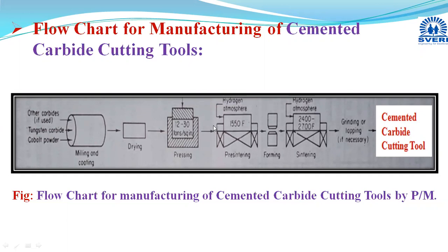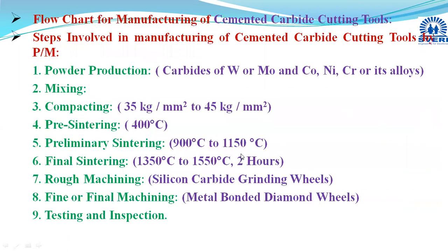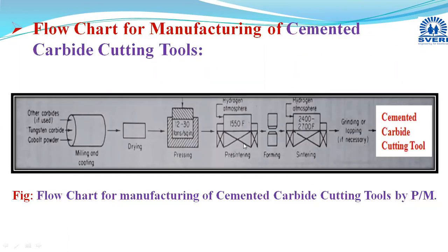Pre-sintering is done to remove the lubricants which you have added in the mixing stage for helping the pressing operation. That oil is eliminated by doing the sintering at 400 degrees Celsius, and then sintering is done in the temperature zone 900 to 1150 degrees Celsius. If required, the sizing is done before the final sintering operation. Sizing is done, and then it is given to the final sintering operation.